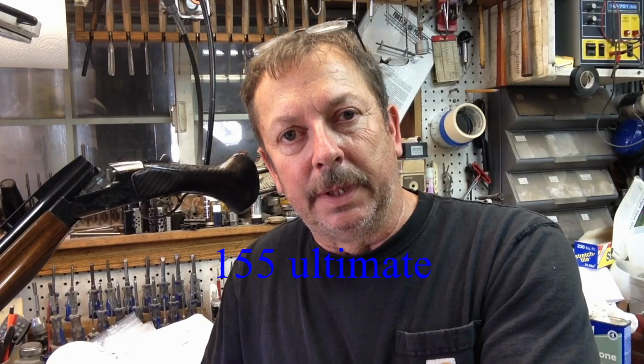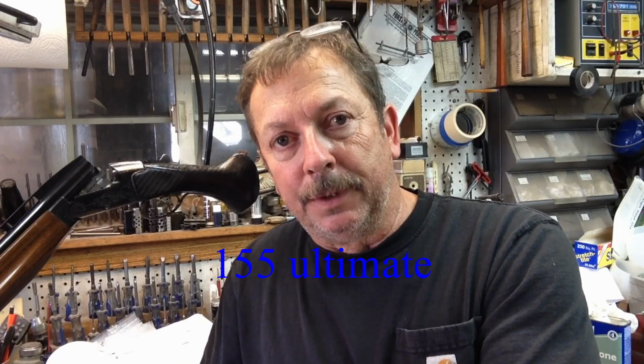Anyway, my supplier showed AVEX A4s, or 1/8 inch rivets, at 155 ultimate shear. They show a little bit higher than what Zenith is showing in the construction standards here. So, close enough, it's not going to make any difference. A standard all aluminum bucked rivet, Zenith construction standards show it in kilograms. Let me look here. They show it at 160 kilograms. When you do the conversion, it works out to be 350 pounds.